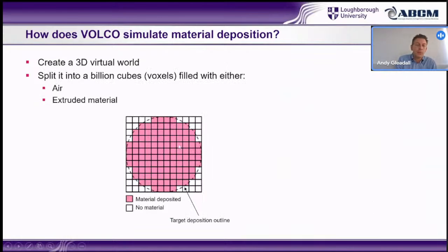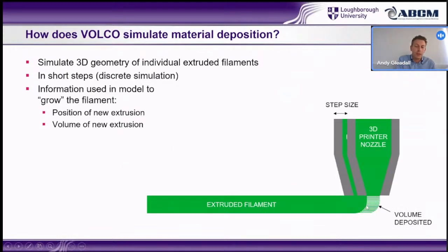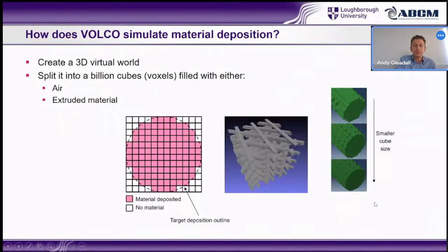We can have a very simple criteria of just looking for whichever voxels in this 3D environment that I create full of voxels, which contain either air or material. It will search with a gradually increasing spherical region and put material in until we've got enough material, as we expect from how much we've told the printer to extrude. This is showing the actual voxelated model, and clearly if you choose tiny voxels then you'll get much higher resolution for your discretized structure.